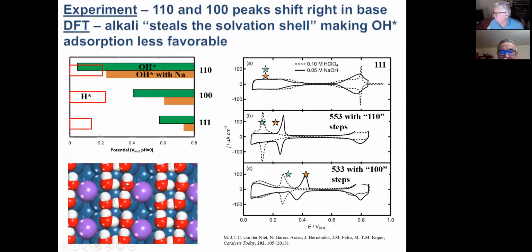And you might look at that and say, well, that's a negative OH interacting with a positive sodium. But OH on platinum is a very covalent bond. It's not very negative. It really likes to be solvated. It forms strong interactions with water. And it doesn't do that nearly as well when sodium's around, because all of that water does not want to line up and form nice hydrogen bonds.